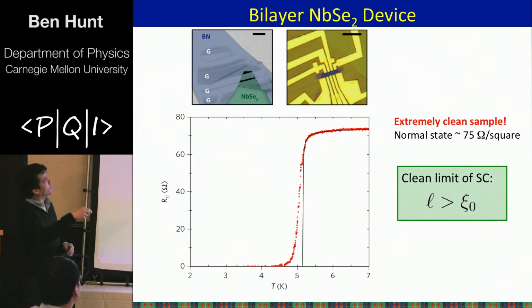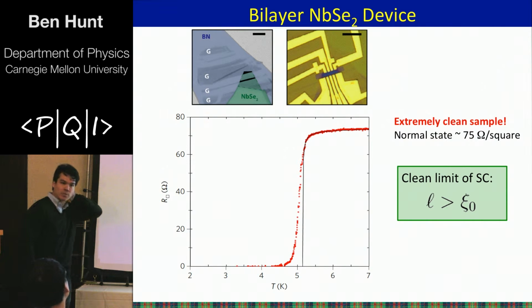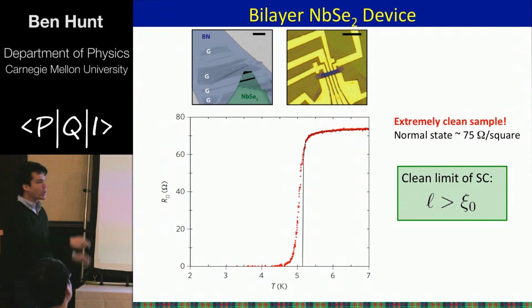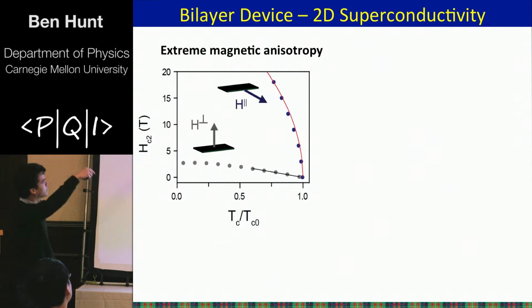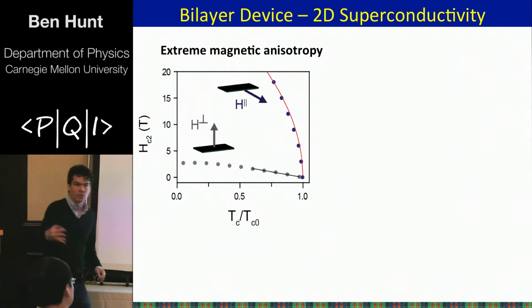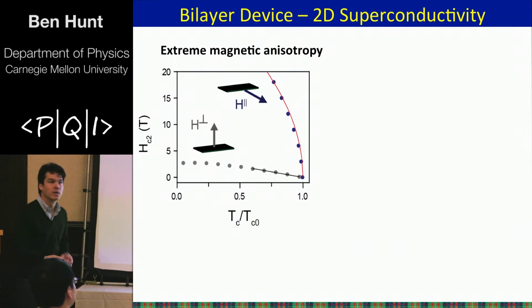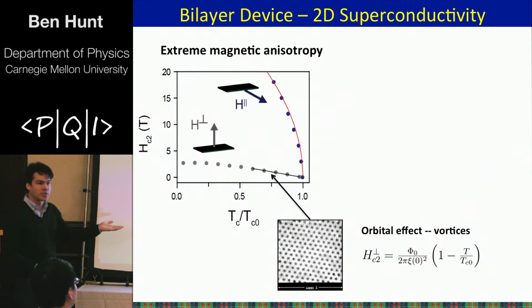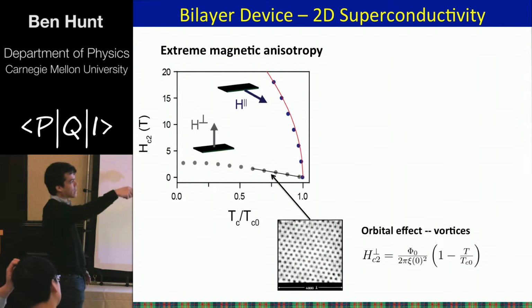This shows the extreme magnetic anisotropy of a two-dimensional superconductor. So if we apply a magnetic field perpendicular, we can quench the superconductor very easily. So this is Hc2 versus T. This is because of the orbital effect. As you heard from the last talk, the way that the magnetic field will penetrate the samples, or the rotation field in that case, is in vortices. And so when there are enough vortices in the system, you quench the superconductor, and that's this line.